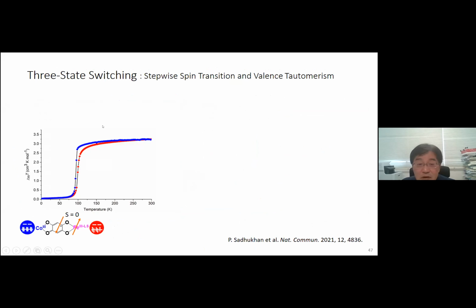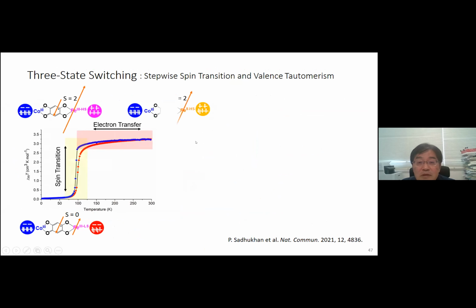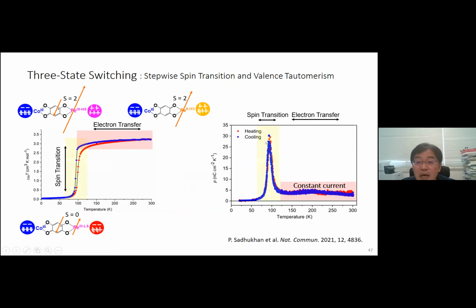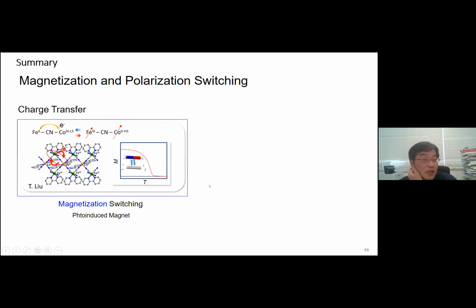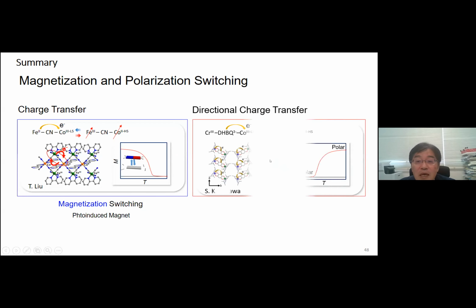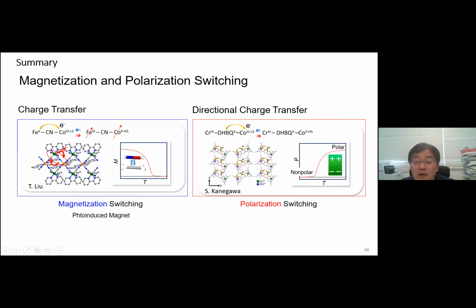And this is an interesting compound. Spin transition occurs at around this temperature, and then electron transfer is induced. And this is detected by current, as shown here. So in summary, many magnetization switching materials have been reported, and now we report a polarization switching